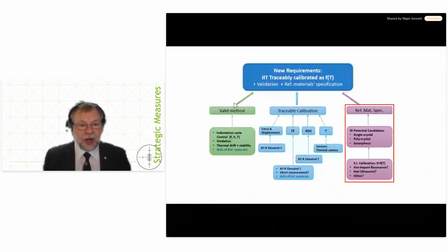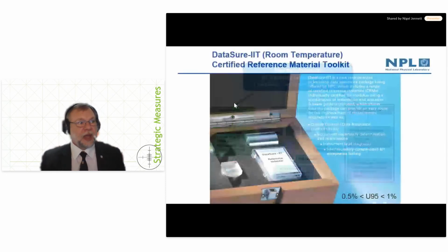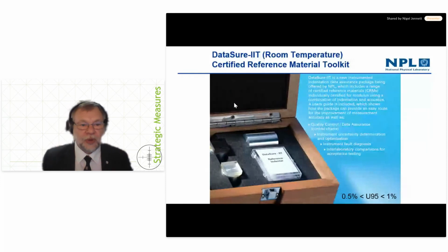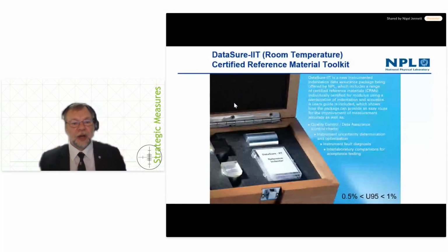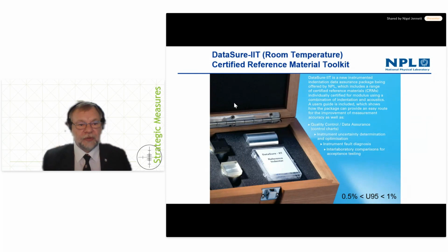Great. So we know how to do this. We've got a reproducible contact method. We've got a method of detecting whether we've got to the right thing. What we really need now are properties that are in a certified reference material at temperature. Well, at room temperature, we can go to NPL and we can obtain, for a price, their certified reference materials. And they have a very low uncertainty in elastic modulus, and they give you a Poisson's ratio as well.